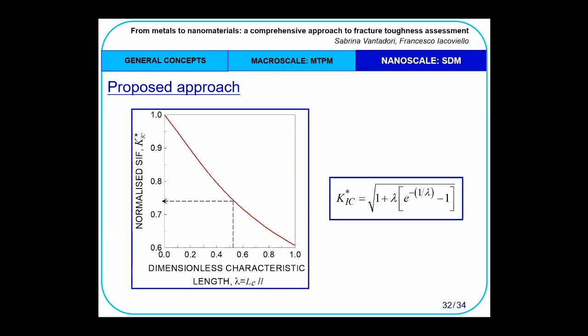In this slide is reported the fracture toughness normalized with respect to the classical solution against the dimensionless characteristic length, lambda. It can be observed that the proposed procedure is able to capture the above size effect, and by entering in this graph with the given value of lambda, the value of the fracture toughness can be simply obtained.